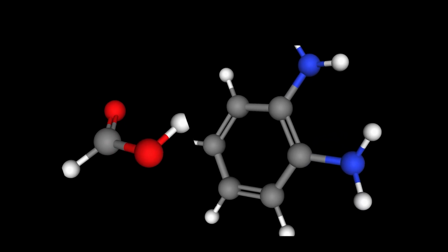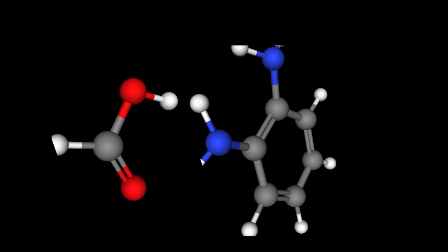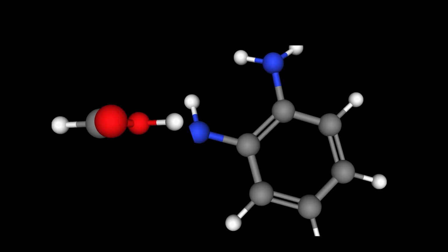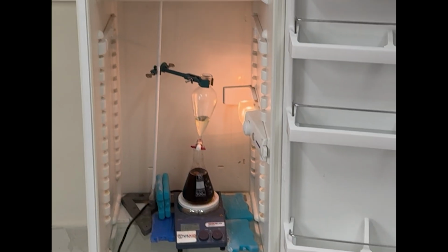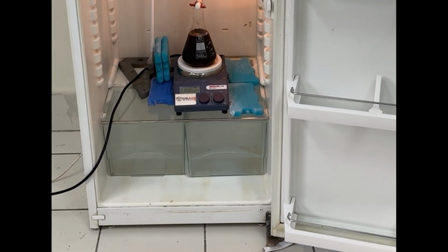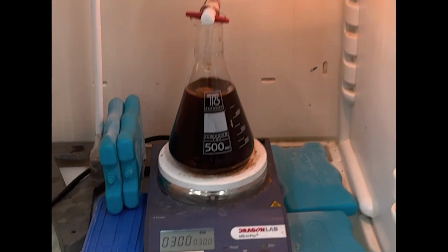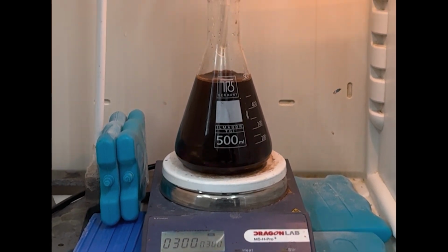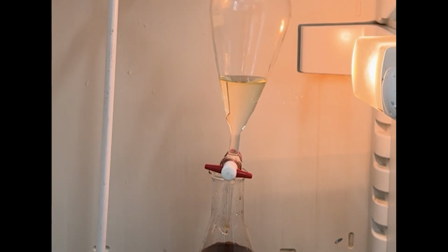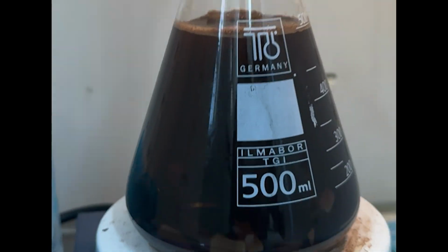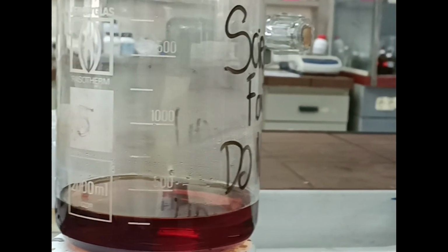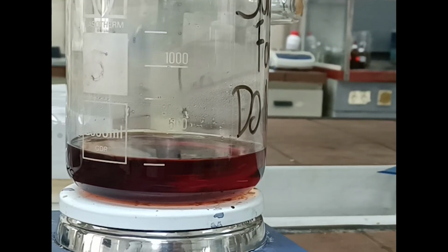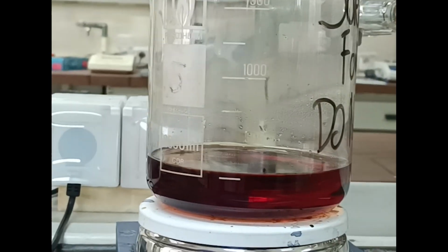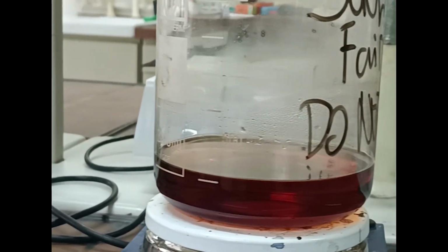Mechanistically, the chemistry happens in two temperature-dependent stages. At low temperature, one of OPD's amino groups attacks the protonated formic acid, forming a monoformamide intermediate. Then the interesting part happens at around 90 to 95 degrees Celsius. You get it to almost boiling point, but you don't go over the threshold. It is when the second amine attacks intramolecularly, closing the ring. And after losing water, it turns into the thermodynamically stable benzimidazole.